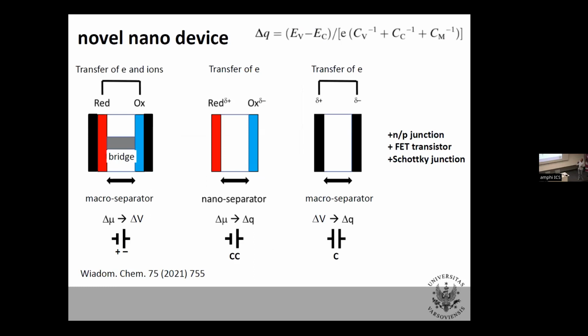What is therefore doing our job? Well, it is the difference of chemical potentials, not electric potentials. So if you take an electrochemical cell, you have a difference of electric potentials, and your separator between electrodes is really macroscopic or microscopic at best. You can use this to get energy. If you now rip out all the inside and you leave 2 electrodes, you will be left with a standard physical capacitor. Now, you must apply a difference of electric potentials to get charge separation.